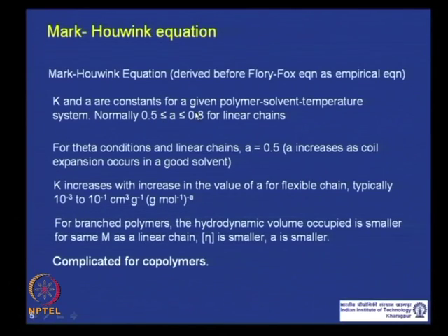So, these values also will change. Normally, A lies between 0.5 to 0.8 for linear chains, and if you have very stiff chains like rod-like, then A can move up to 1, but for linear flexible chains it will be between 0.5 to 0.8.